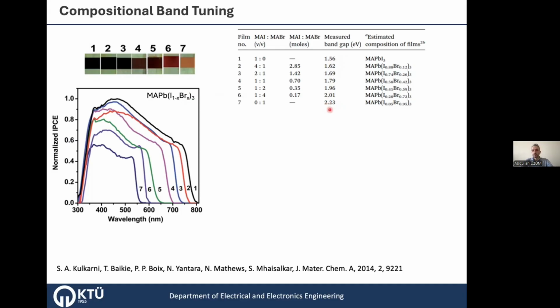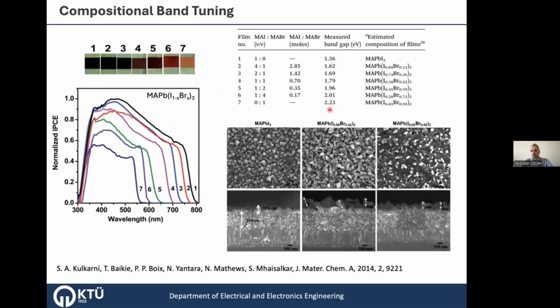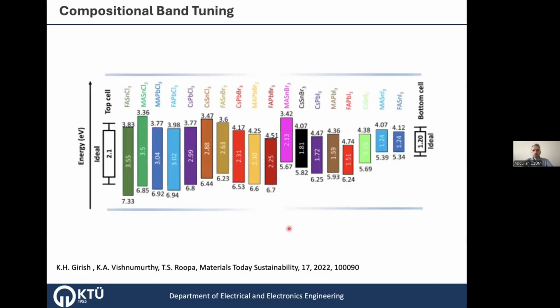Okay, so if we look at the crystal structure, or the perovskite surface, you can see the uniform structure of the methylammonium lead iodide surface, and with increasing bromide content, the crystal structure actually changes, as you can confirm in these images. So here in this chart, it is shown with different cations, different metals, and different halides with different compositions, you have different band gaps with different LUMO and HOMO levels. You can think of it as conduction and valence band.